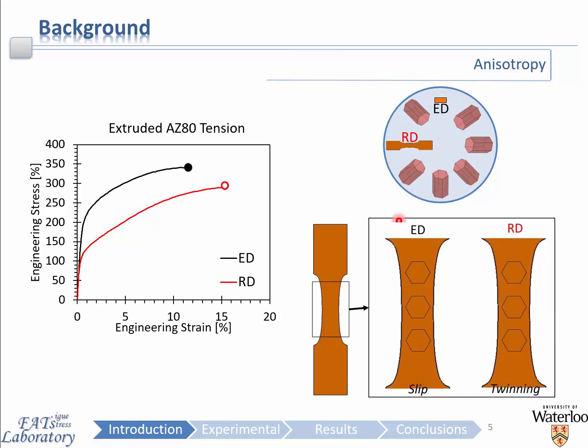When deformed in tension, a sample taken from the extrusion direction will exhibit basal slip, and monotonic hardening is indicated by this black curve on the left. However, when deformed in the radial direction, basal slip is not favorable and extension twinning happens instead. This manifests itself as a sigmoidal hardening behavior once again, and a premature yield stress. So important to note here is that the material behaves vastly different in monotonic tension depending on the direction in which you are deforming it. So this anisotropic nature of magnesium will subsequently be discussed in more detail.